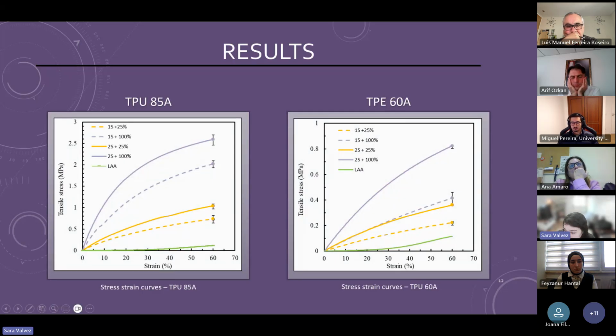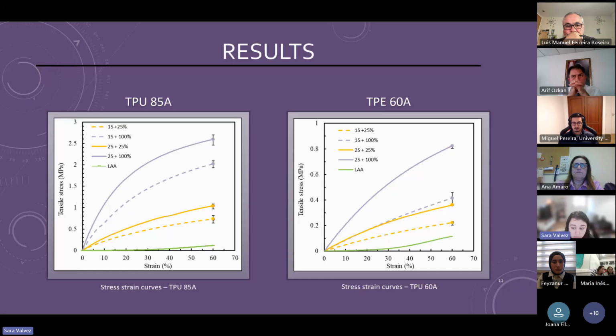As it is possible to see, here we have a stress-strain curve of the left atrial appendage that is compared with the stress-strain curve of our printed samples. So it is possible to observe that the closest material in terms of maximum stress values is the TPE 60A with 1 shell and 25%.